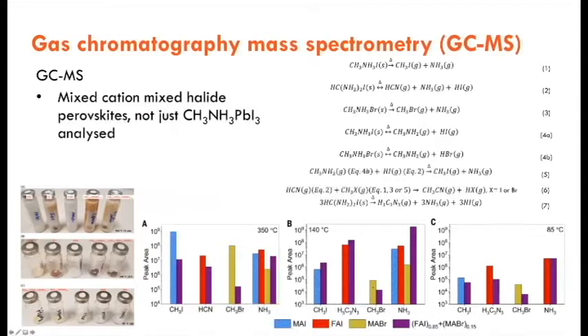But in this case, we don't need to analyze the lead halide salt because they won't give out any volatile products. So we analyze the 4 precursors. So the methylammonium iodide, the formamidinium iodide, and the methylammonium bromide, and then the mix. So the mixed cation, the mixed organic cation, and the mixed halide, they are the sort of state-of-the-art perovskite materials for the high-performance cells. So we heat those precursors in a bottle at different temperatures and look at what happens. So look at what comes out.